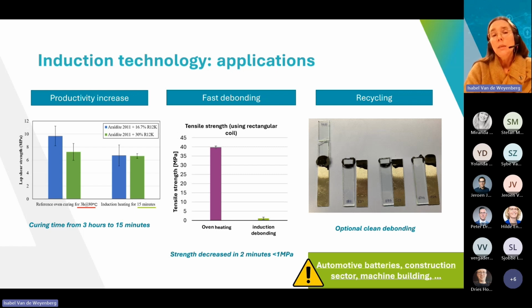And when we look at the debonding possibilities, this is now another sample than in the first graph. When we have a fully cured sample, well, if we put it in an induction field for only 2 minutes, you see that you can decrease the strength below 1 megapascal, and that's the strength with which you can just tear your parts apart with your bare hands.